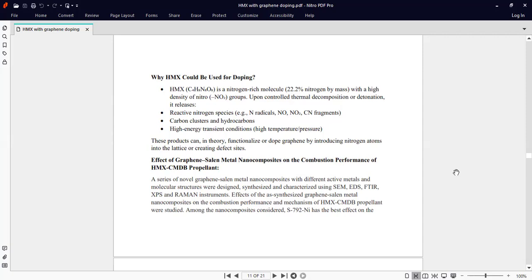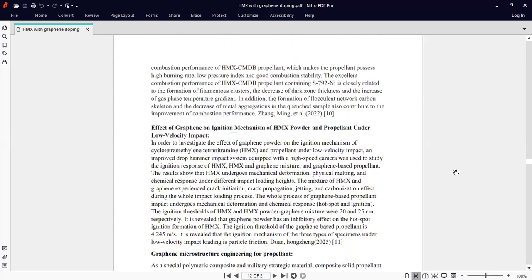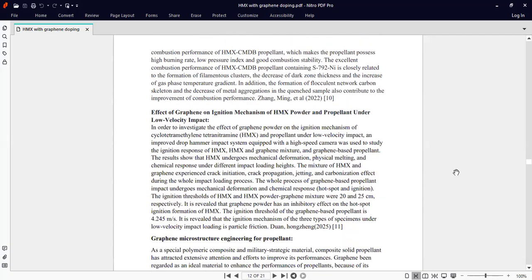The effect of the as-synthesized graphene-salen metal nanocomposites on the combustion performance and mechanism of HMX-CMDB propellant was studied. Among the nanocomposites considered, S-792-Ni has the best effect on the combustion performance of HMX-CMDB propellant, which makes the propellant possess a high burning rate, low pressure index, and good combustion stability.